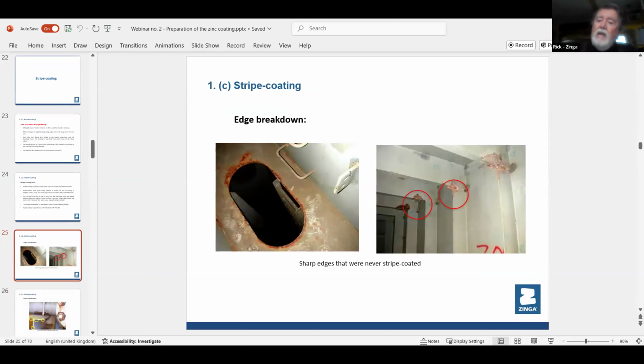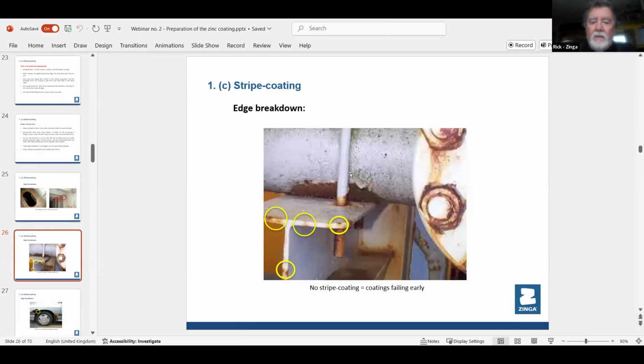This is just to show an example. You can walk into any ship that's maybe 10 years old, and you'll see this on all the access hatches immediately. And I'm talking any ship anywhere in the world, you see these things because they were not stripe coated originally. These edges, even on a pipe support inside an oil refinery, had edge breakdown there. And of course, that pipe you can see had crevice corrosion because you have two metallic surfaces close together. Overnight condensation was sitting on the flat part, and it was going inside that joint and corroding the two surfaces. So if that was blast cleaned, you would stripe coat the edges that have been ringed off there where it's rusting, but you would also stripe coat inside that crevice joint. So you would not see that crevice corrosion taking place at all.